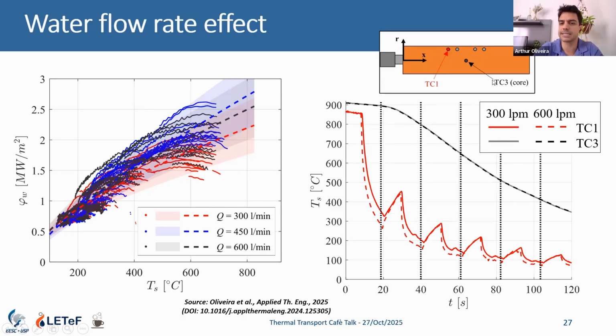So after a new test with a thermocouple in the core - because if we have very different heat transfer conditions, we should see a temperature difference in the core of the material after a while - when we did the test, after 2 minutes of cooling there is no major difference in the temperature measurement in the core of the part. You can see that after a 500 degree drop, there is only 2 degrees difference between the two tests for the two flow rates. So there is no major effect of the water flow rate in these conditions, of course.